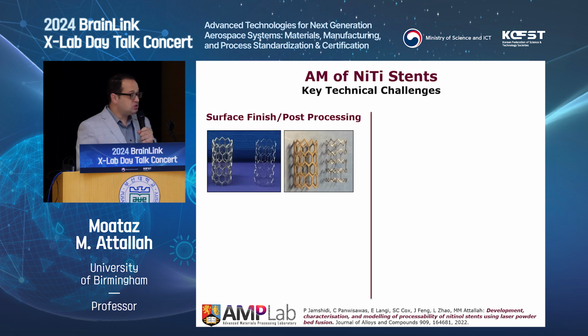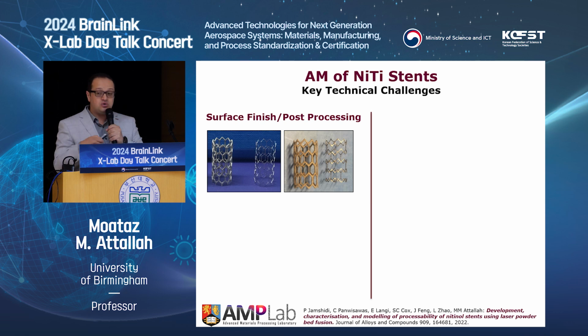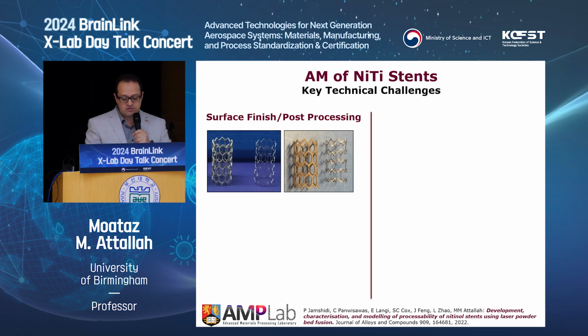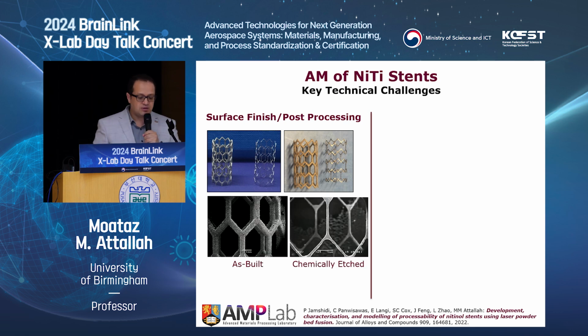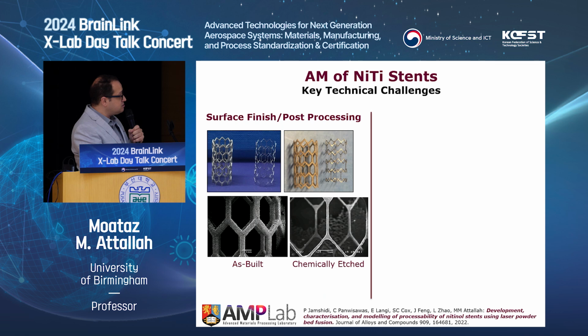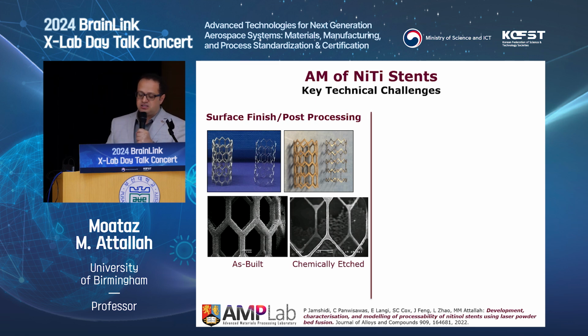If you look at the as-printed stent, this is how it looks, the top there. It then had to go through a long process of surface finishing and electropolishing to get to the nice, shiny stent surface. And if you see this under the SEM, you'll find how an as-built stent looks. It's around 0.5 mm, this scale bar. But after etching, it reached the right geometry of around 80 microns, which is what you want for a nice bendable, flexible stent.